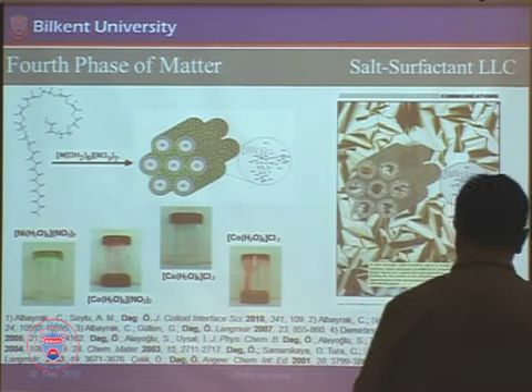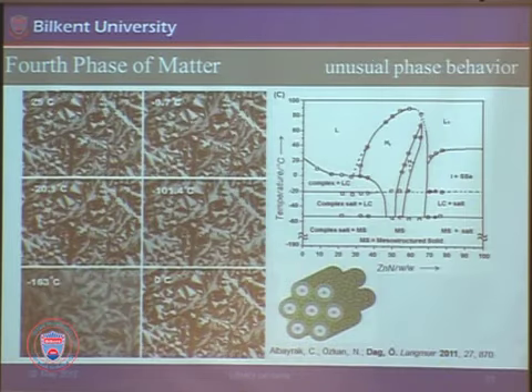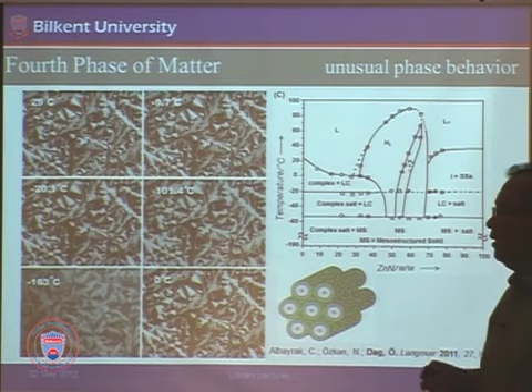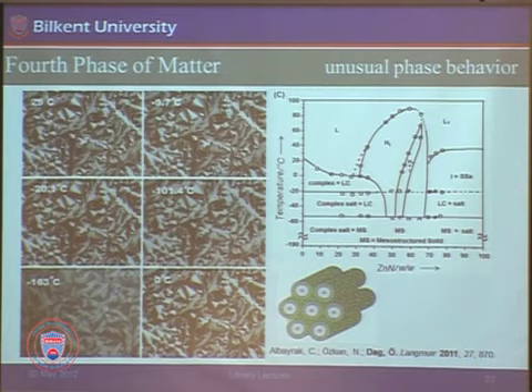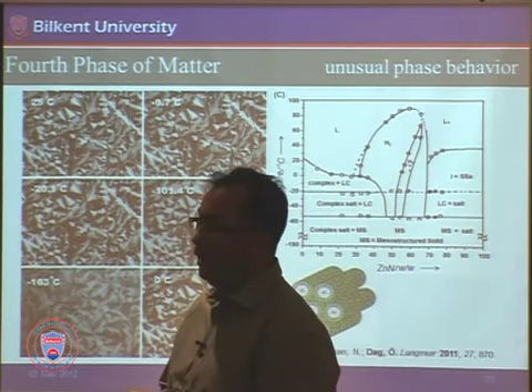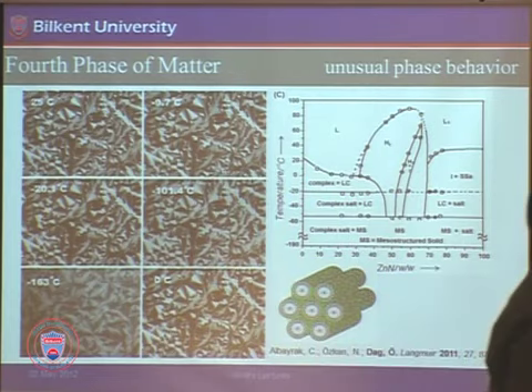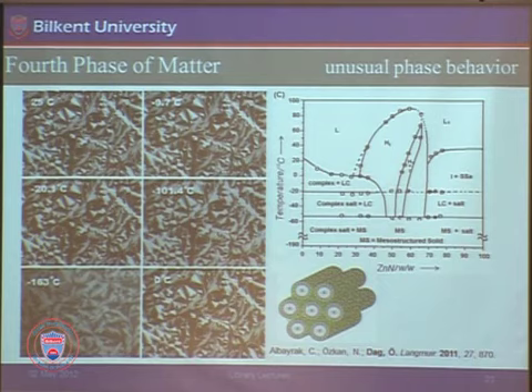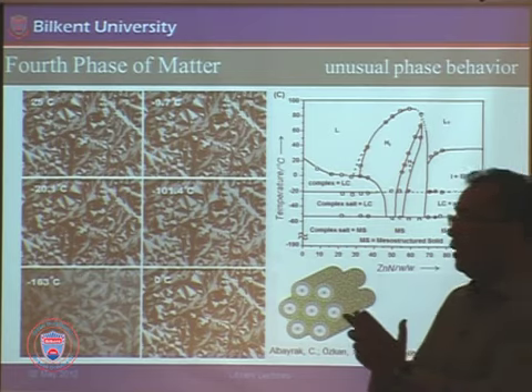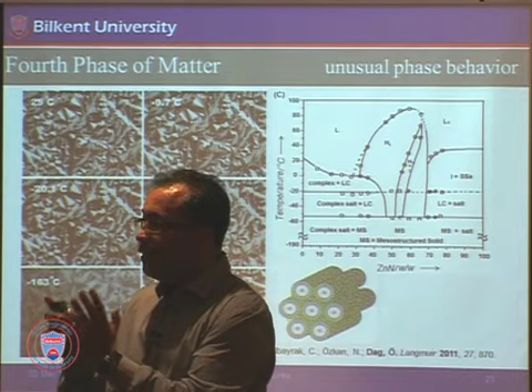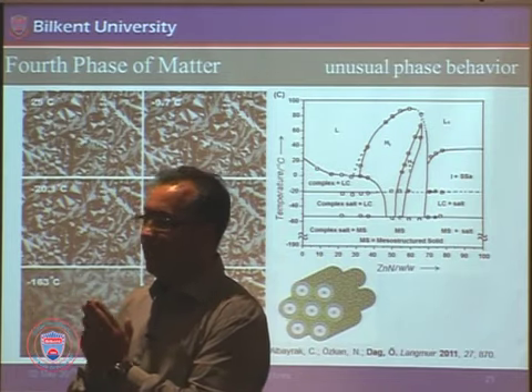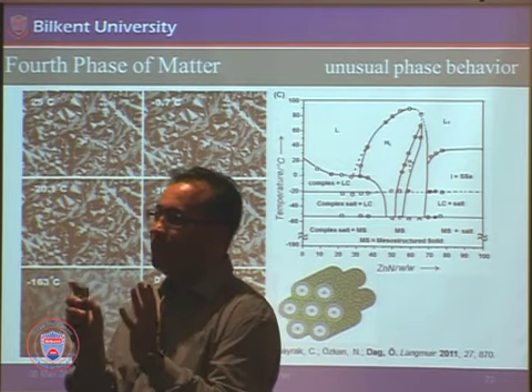They form nice gels. And later, as I said, when I look at the history of science, progress going from one state to another was taking tens of years. After 10 years, maybe a little more than 10 years, we discovered that those salts go into a melt phase and behave like any other solvents. They melt when you put them in such a small space. This is called the confinement effect. When you reduce anything to small size, its melting point drops drastically. Anything small melts easier. By small, I mean a few nanometers.